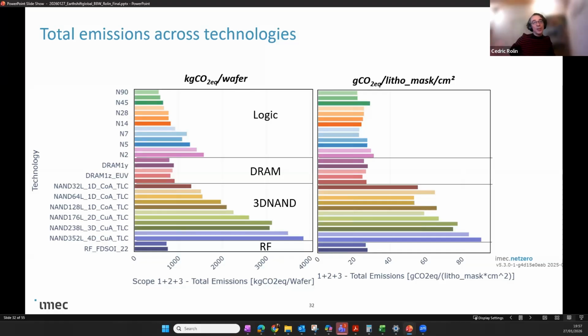The wafer is going to be cut in order to recuperate a certain amount of dies. Some of those dies are going to yield, and some are not going to yield. Generally speaking, the bigger the die, so if you make very large chips, the yield is getting worse. And so the gram CO2 equivalent per square centimeter obviously is going to increase across generations. So definitely the footprint per square centimeter for 2 nanometer technologies is larger than for N90. And that's because there's more processing that's done to create, let's say, the same area of wafer.